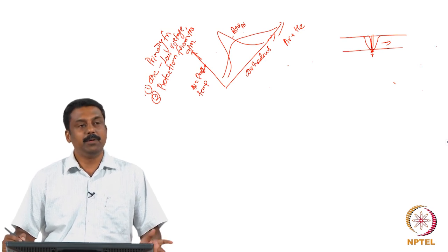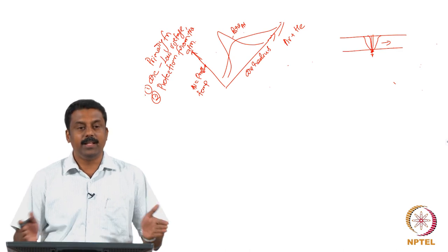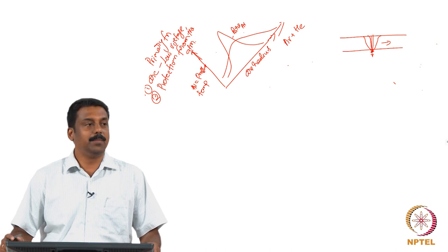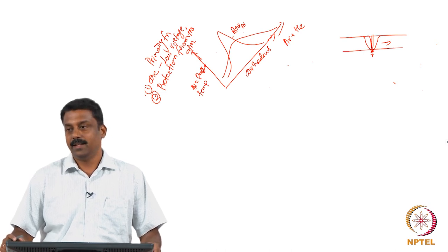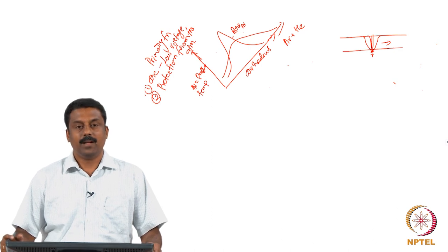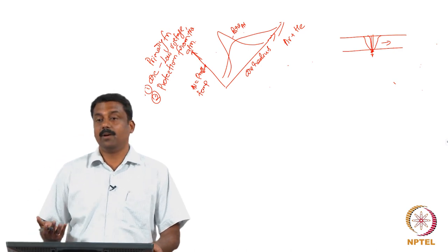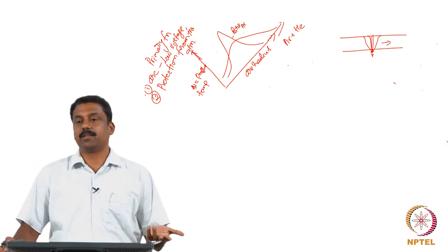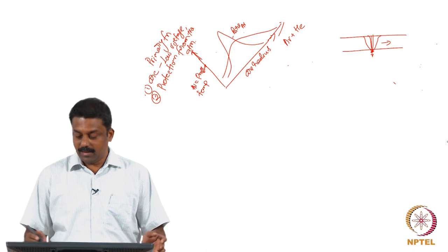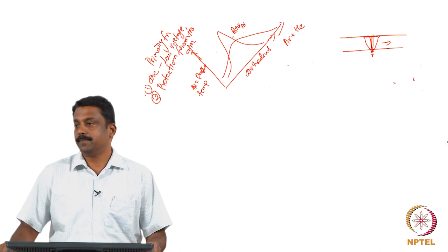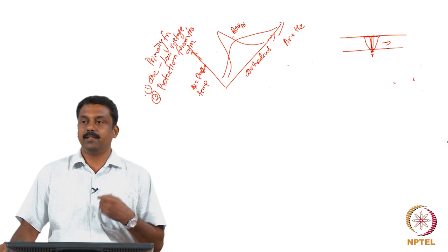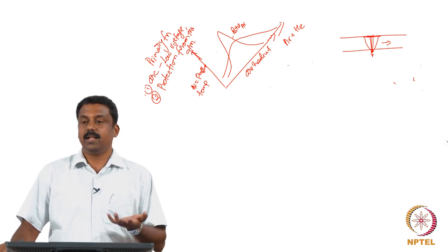In this case you need to distribute the heat in the arc. You can add high conductivity gases - you can add helium into argon, or for austenitic stainless steel you can also add hydrogen. Five percent hydrogen added to argon is commonly used for austenitic stainless steels to effectively distribute the heat so that you can increase the weld bead width. These are all the secondary considerations commonly used while selecting the shielding gas.